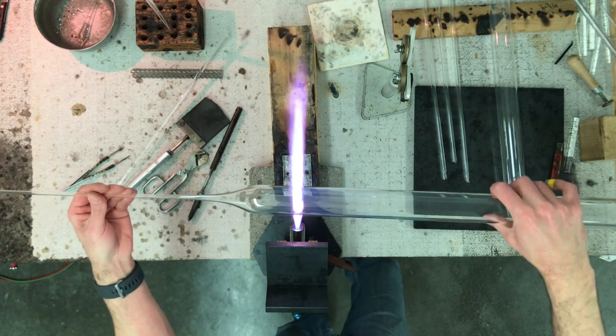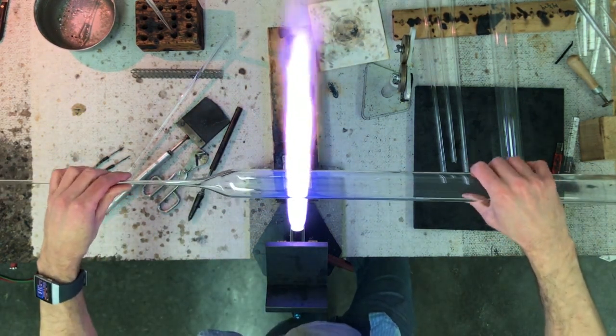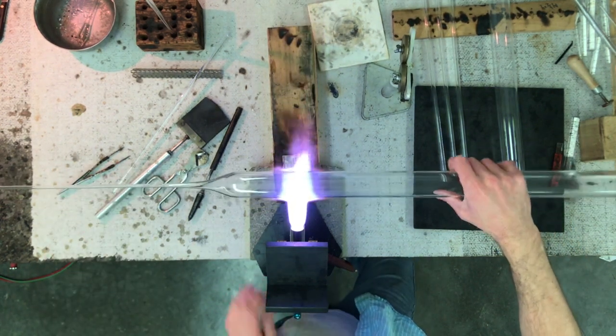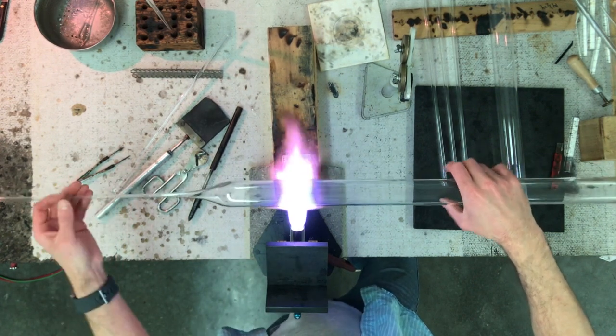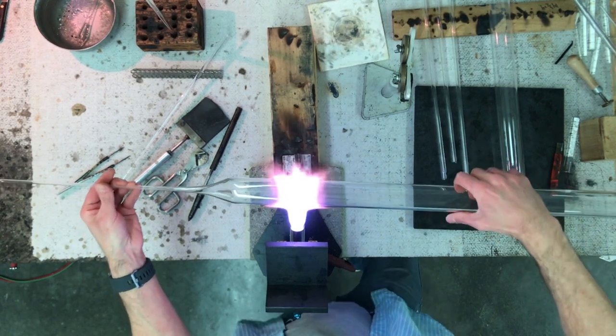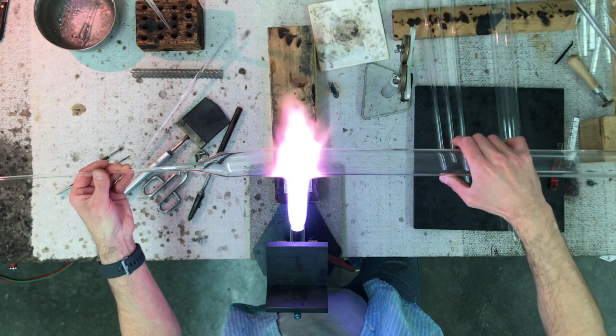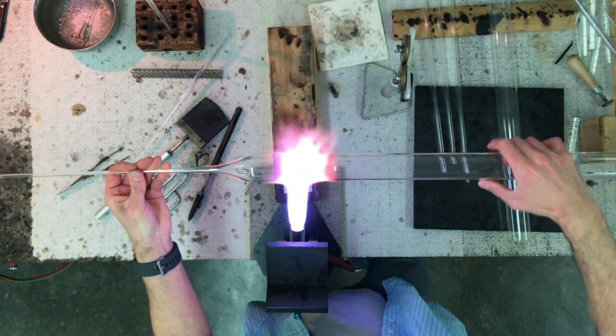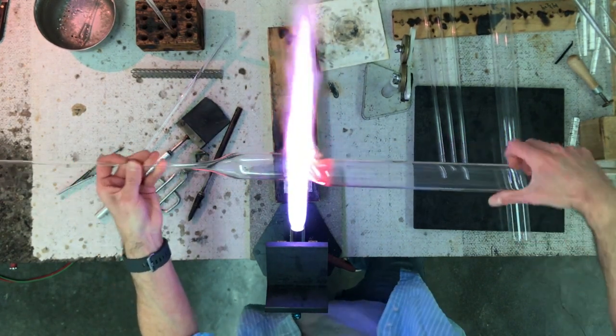So I'm just straightening this. Whenever you have a blow tube or a point handle and you're trying to straighten it up, you put the heat on that shoulder, just where the straight tube starts to transition down, and then move that area on center. If you put too much heat towards the blow tube and try to straighten it there, is it going to work out so well?